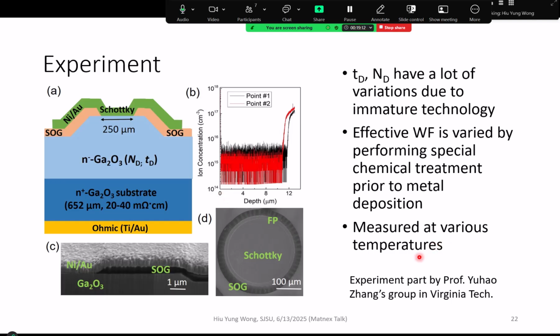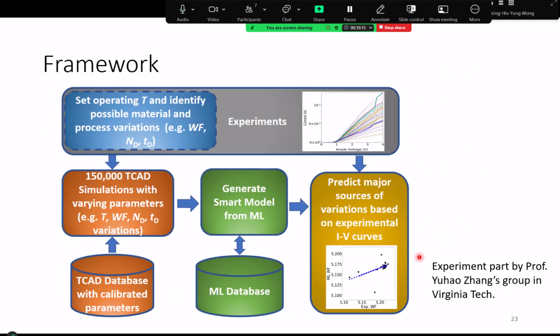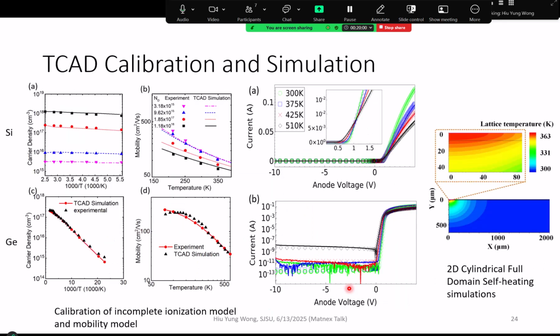They also measured it at various temperatures. So we get a bunch of data that is a result of different thickness, different doping, different measurement temperature, and different work function. So our idea is, okay, now let me do a TCAD simulation. And we worked very hard here at San Jose State University. We spent 2 weeks to generate 150,000 TCAD simulations for this structure. And then we build a machine, feed in their data, and try to predict the work function, the temperature, the thickness, and the doping variation in that structure. Okay, here I will do it quickly.